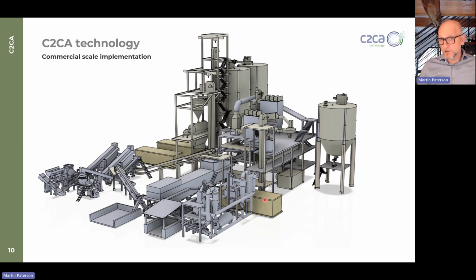So I already talked about our first commercial scale plant. This is how it will look like. The engineering is done. And on the last slide, I will give you more details about the project, but you can find some of the machines we just saw on the pictures. So this is the ballistic separator. Here you start with a two-stage crushing process. You go into the ballistic separator, you take out the RCA, you go to the thermomechanical separator, 2 units here. You take out the RFA, and then the fines are collected here. You feed them into a mill. It's a ball mill, which you see here in the back. After the mill, it goes to the carbonation tower, and from the carbonation tower into the storage silos.